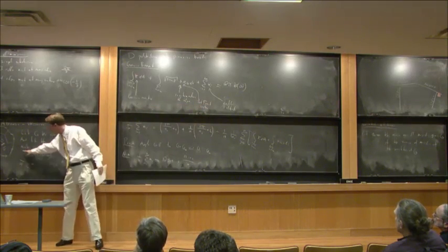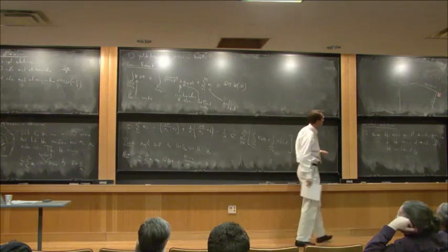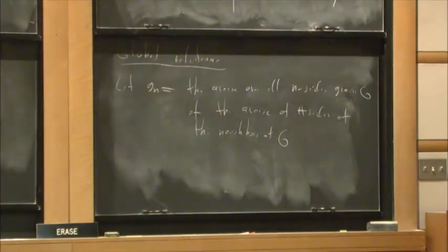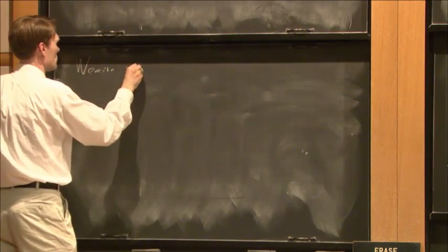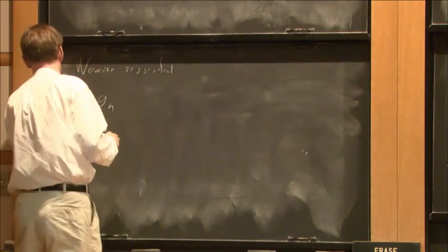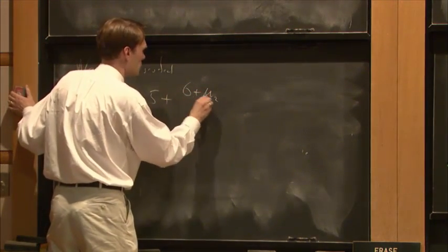Namely, you take the whole subdivision of the plane, and then you look, say, for all 5-sided grains, and for each of them, you compute what the value would be of the law, like the average, and then you take the average of all of them, or rather, for mathematical purposes, you take the expected value of all these averages. And then Weaire suggested that the correct law should be Gn is about equal to 5 plus (6 plus mu2) over n,